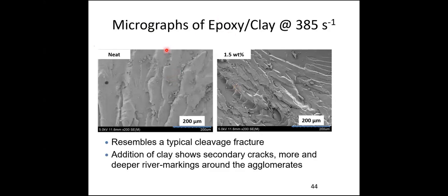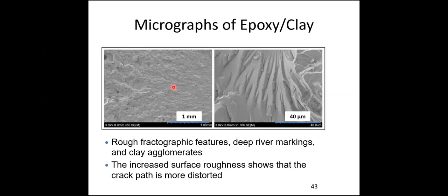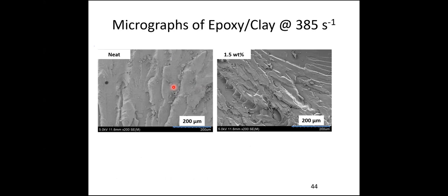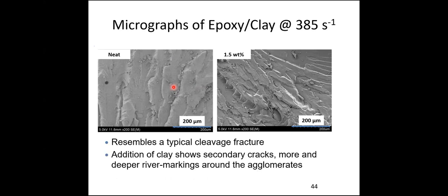So again, this is the micrograph which we took from the high strain rate samples. If you see at quasi-static, the samples were very smooth. But when we see the fractography at high strain rate, you can see a typical cleavage structure and a very rough surface. So what I want to convey is that the addition of clay shows secondary cracks and more deeper river markings. This is what we could see.